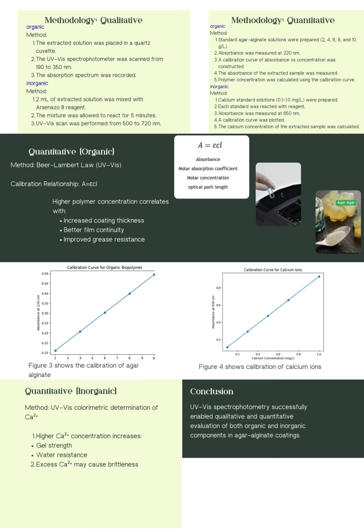For the quantitative inorganic analysis, calcium standard solution was reacted with the reagents and measured at 650 nanometers. The calibration curve allows accurate determination of calcium ion concentration in the coatings, and the result shows that calcium concentration plays an important role in improving water resistance, although excessive calcium may reduce the coating flexibility.